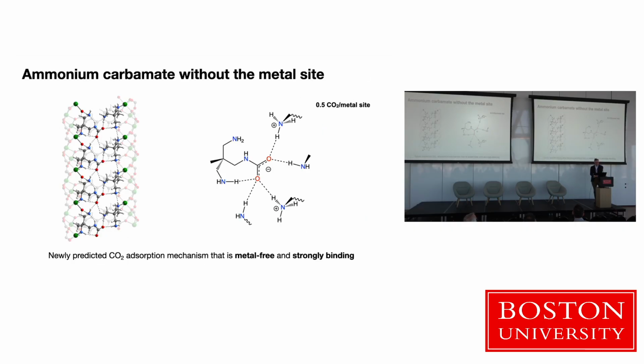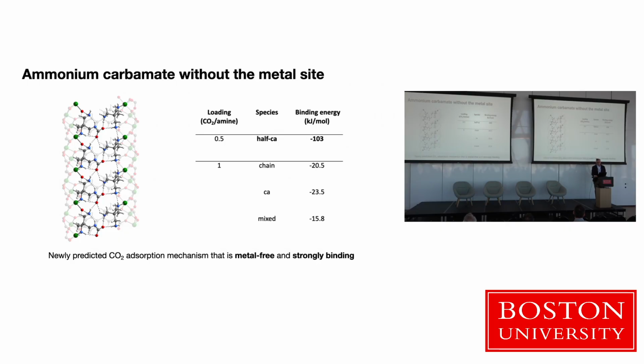So this gives you a sort of punchline here, a couple slides. What we found after doing some simulated annealing with this potential is that when you introduce CO2 into this environment, it doesn't displace a metal atom. It just bonds in the pore, and it bonds in a very strong way, with, you can see, 5 hydrogen bonds involved. And so we have this ammonium carbamate formation, but no metal site displacement. This is an unusual structure that hadn't been seen experimentally. And it's very interesting. It has a very high binding energy, but unfortunately, the binding energy for additional CO2 is very small. So it doesn't look like you're going to be able to put more than half a CO2 per metal site, which is actually a step backwards.